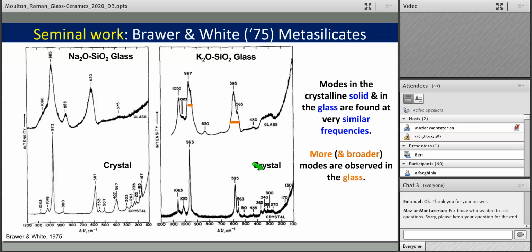What one can observe is that the main intensity features, for instance, this peak around 970, 980, this peak around 600 wave numbers, and this peak here around 300 or 400, seem to be the same vibrational modes in the crystal and in the glass, but there are some differences.